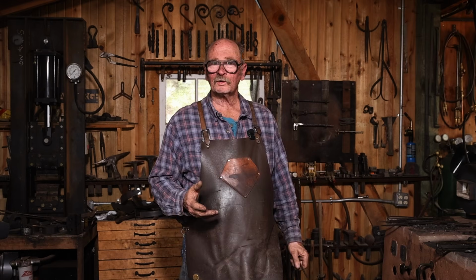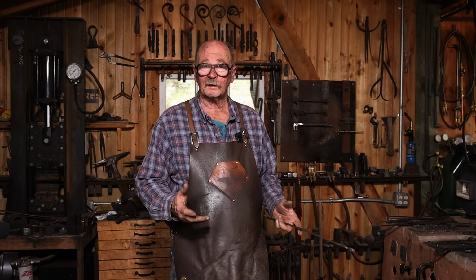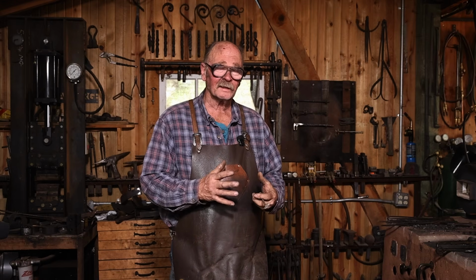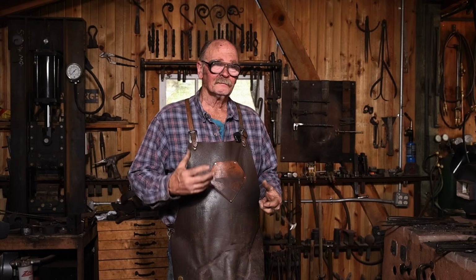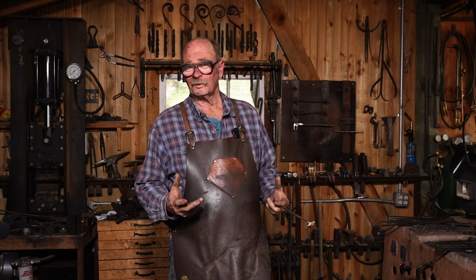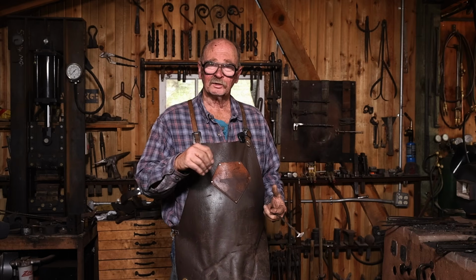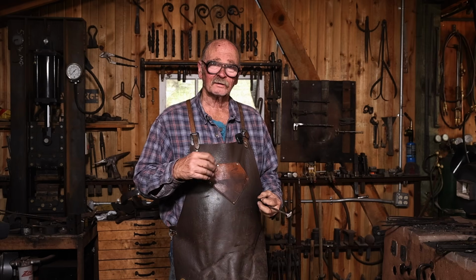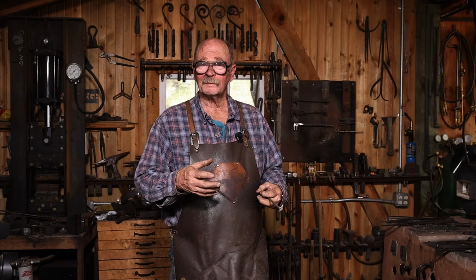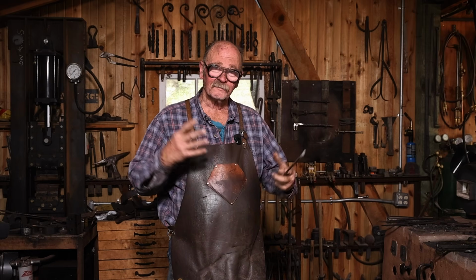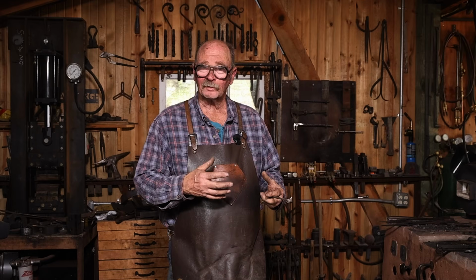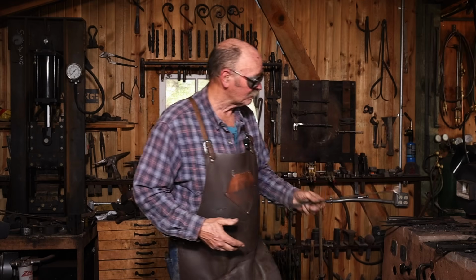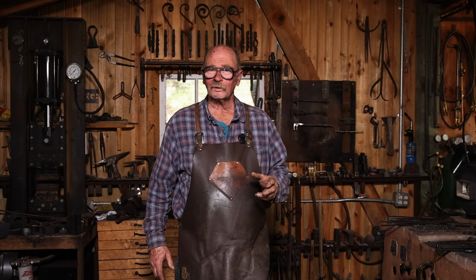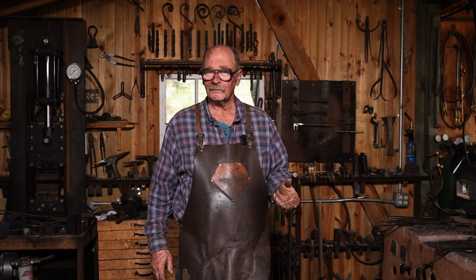Now, a perfect forge weld should be as strong as the parent material because you're fusing it together. It's hard to tell if you have a perfect forge weld, though. If you have any inclusions, any scale, trapped flux, things like that, it may not be perfect. And as you start to refine the weld, if it isn't perfect, this kind of thing can happen. But for most things that you're forge welding, it really doesn't matter that much.